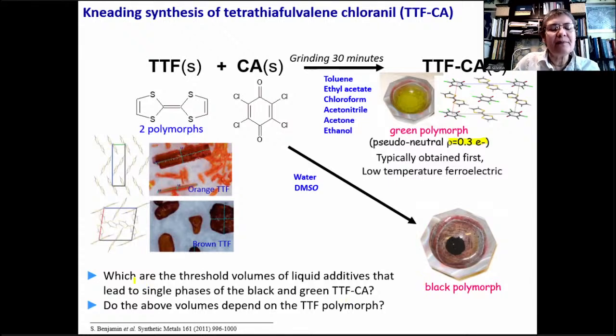So at the time that we studied these materials with undergraduates, the research questions were something like: which are the threshold volumes of the liquid additives that lead to the single phases of the black and the green tetrathiafulvalene chloranil, since often a mixture of them was produced? And do these volumes depend also on the polymorph of the tetrathiafulvalene reactant? So this material, tetrathiafulvalene, the donor, has two polymorphs. One of them is orange in color, and it has the crystal structure that is shown there with these stacks of tetrathiafulvalene molecules. And the other one is brown in color, and the structure is shown there, and it does not have stacks of molecules.